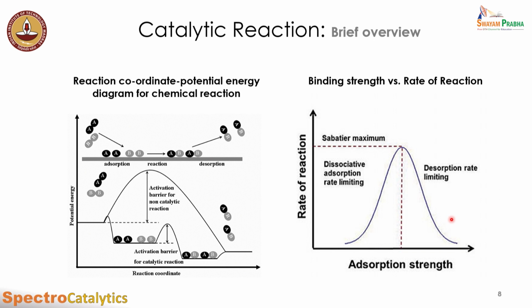So we cannot see the final product, and hence the overall rate of reaction is again low. So we need to have an optimum amount of binding energy such that it's strong enough for the gas phase molecules to be adsorbed on the surface, but not so strong at the same time such that the formed species are not desorbed back to the gas phase. Okay, so that is clear.